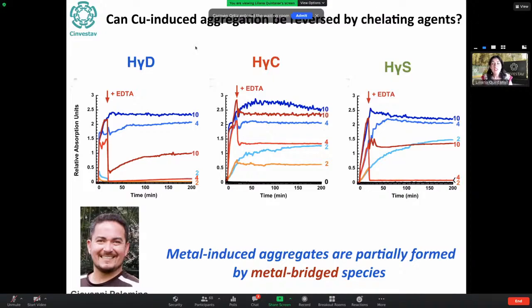So this means that metal bridging is contributing to the formation of these large light scattering aggregates, but it's not the only mechanism. There are other things going on, like we already saw, partial unfolding of the protein that causes formation of the domain-swapped aggregates and species.